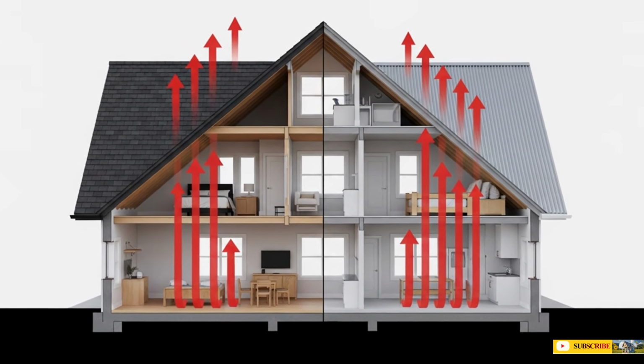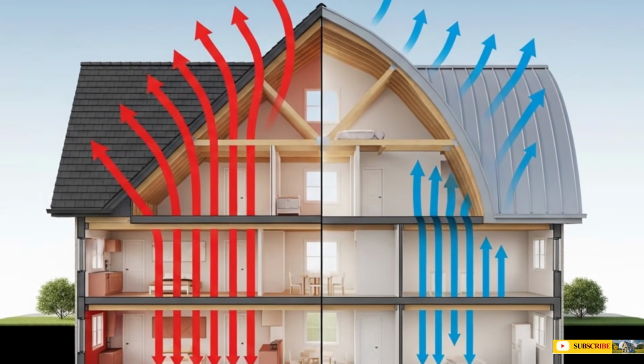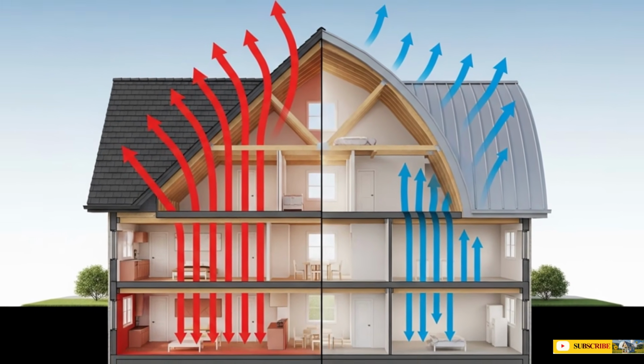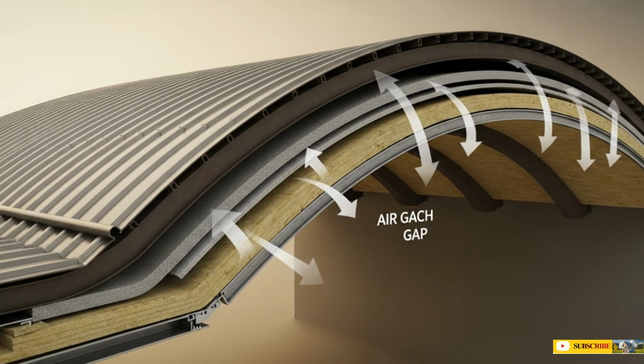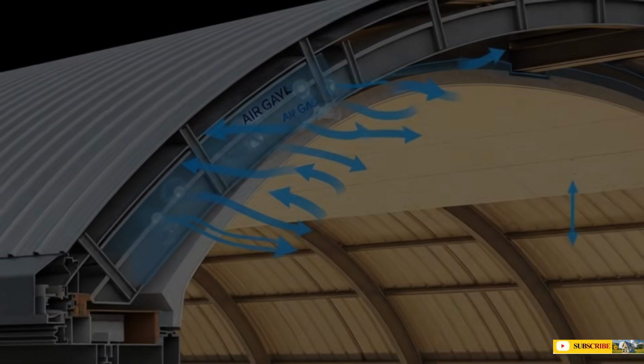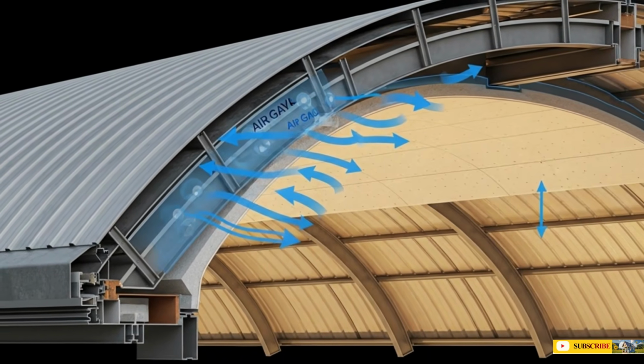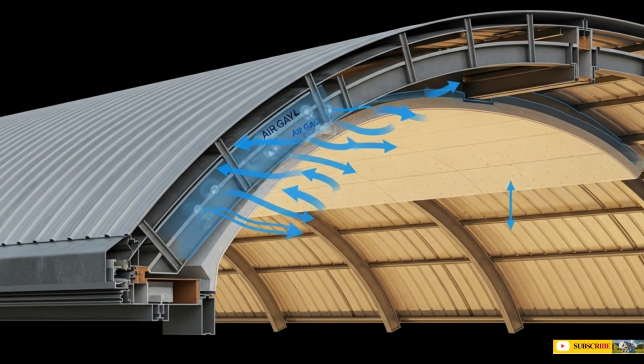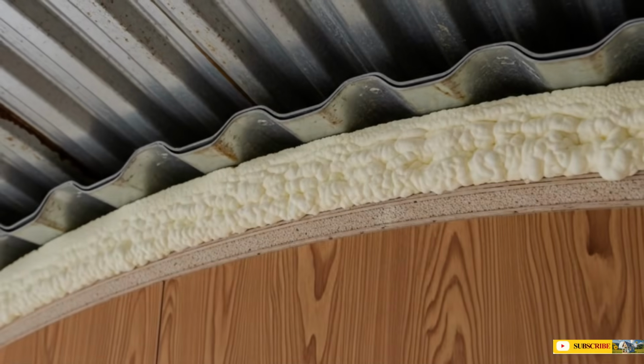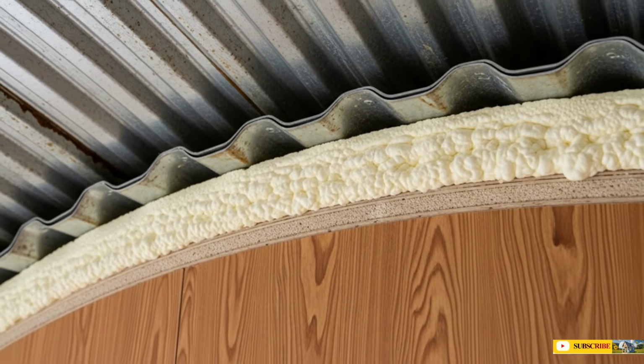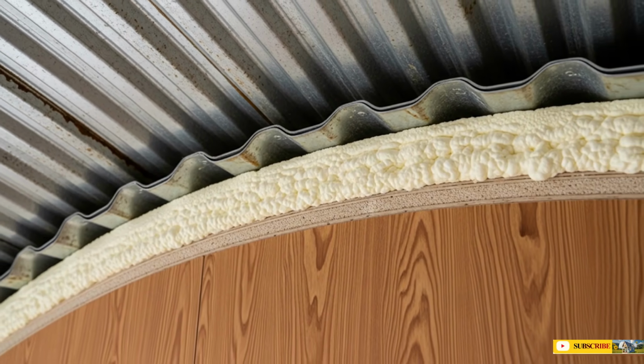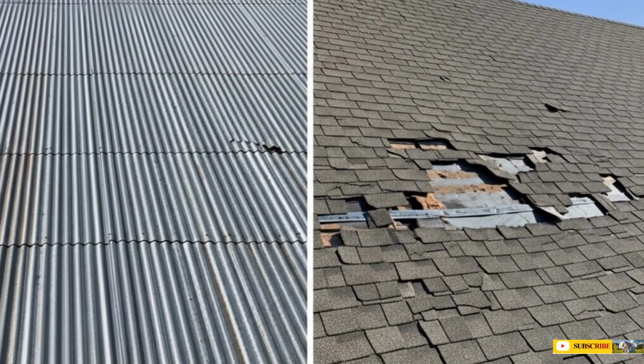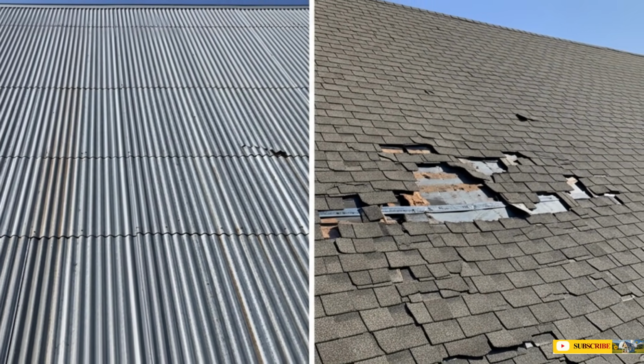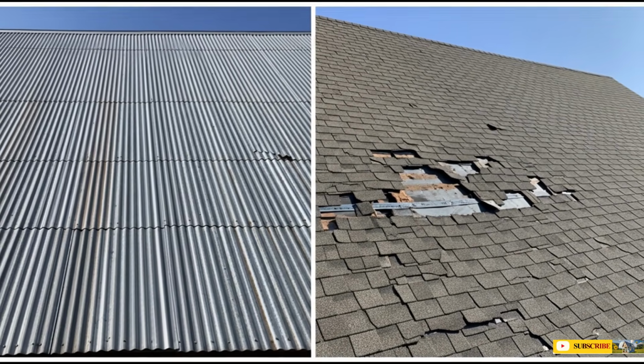Reason 5. Longevity. This is where metal roofing separates itself from everything else. Corrugated metal roofs last 40 to 70 years, depending on the material and coating. Galvanized steel gives you 40 to 50 years. Galvalume, which combines steel with an aluminum zinc alloy, extends up to 50 to 60 years. Aluminum in coastal environments can reach 60 to 70 years. Compare that to the 15 to 25-year lifespan of a standard asphalt shingle roof, and the economics are stark. You may install a corrugated metal roof once and never need to replace it.